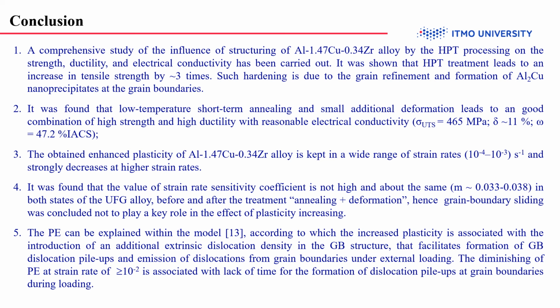The plastification effect can be explained within the model according to which the increased plasticity is associated with the introduction of an additional extrinsic dislocation density in the grain boundary structure that facilitates formation of grain boundary dislocation pile-ups and emission of dislocations from grain boundaries under external loading. The diminishing of the plastification effect at a strain rate of more than 10 to the power of -2 reciprocal second is associated with lack of time for the formation of dislocation pile-ups at the grain boundaries during loading.